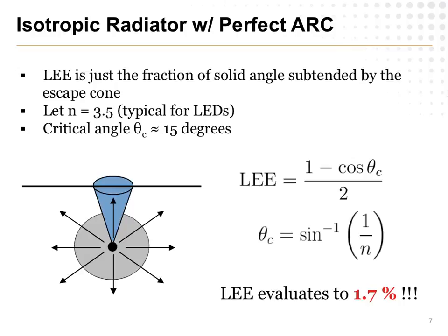For simplicity, you can even imagine, let's suppose there's an anti-reflection coating on top, which will completely eliminate any reflections within the escape cone. A fun fact: anti-reflection coatings can eliminate all the reflection in the escape cone, but outside, there's nothing you can do. So it's called anti-reflective, but it actually can't be perfect in that sense. You can kind of prove from Maxwell's equations that no matter what I do above this plane, I will never escape the escape cone. See what I did there? It'll always be there.